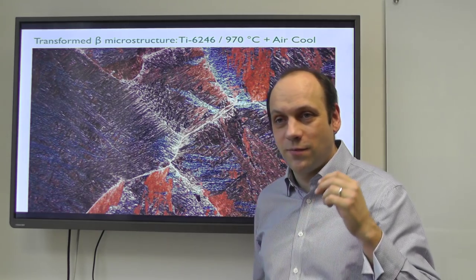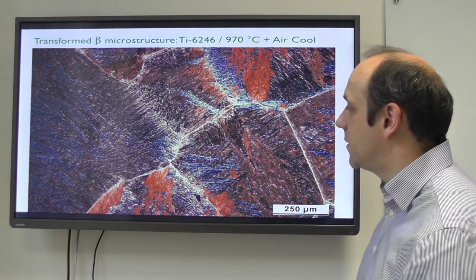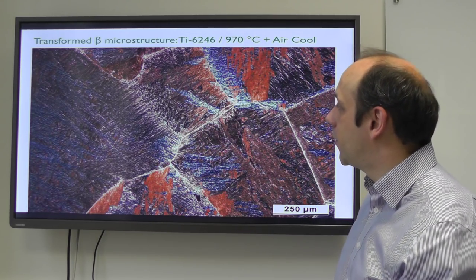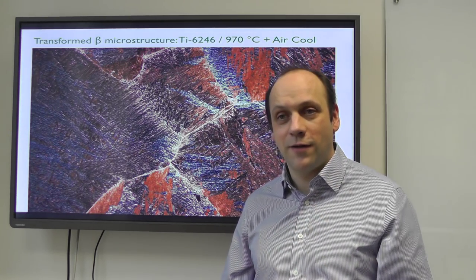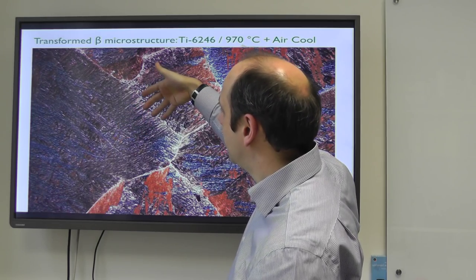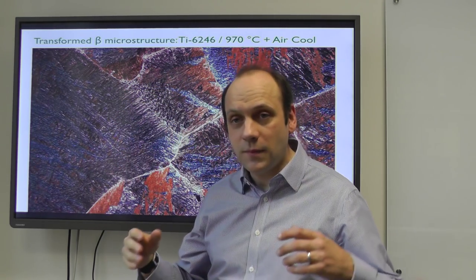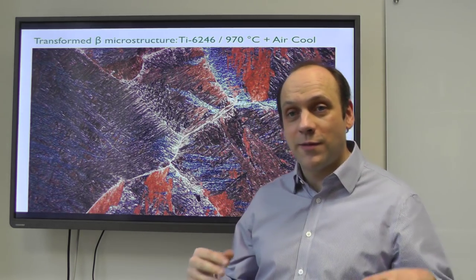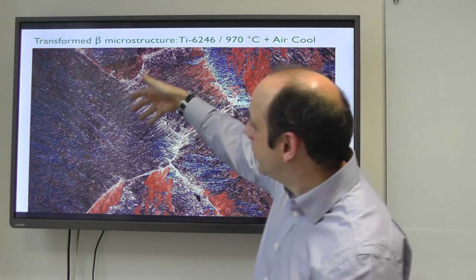The reason the prior beta grain size matters is that the beta grain goes through the transformation to the low-temperature HCP alpha phase from the high-temperature BCC phase. Alpha first forms on the grain boundaries - you can see a slightly serrated grain boundary here with a grain boundary alpha film. If you cool very slowly, that alpha film will be quite thick, and thick grain boundary alpha films tend to give poor fatigue properties. Because the beta grains have recrystallized they don't have many dislocations or defects, so there aren't many nucleation sites. Also, titanium reacts with its own oxide in the melt so there are no inclusions to nucleate from - nucleation is generally quite poor and must occur from grain boundaries.